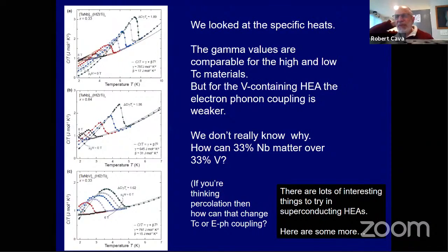Here's the thing that bothers me. When you think about a glass, if the properties of matter are determined by the Fermi surface, why does it matter what atoms give me that Fermi surface? It can only be that the electron-phonon coupling is what matters. But why does an alloy that has 33% niobium in it, or in some cases 20% niobium, have a better TC than something that has 20% vanadium? How does the 20% of niobium wag the dog, as we would say in England? How does that make the TC so much higher in the niobium case than the vanadium case?